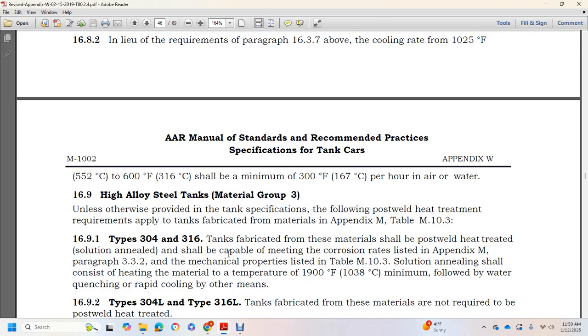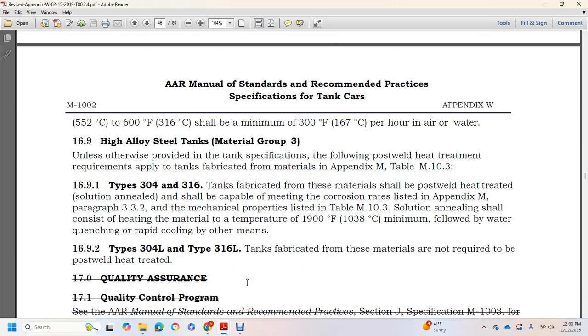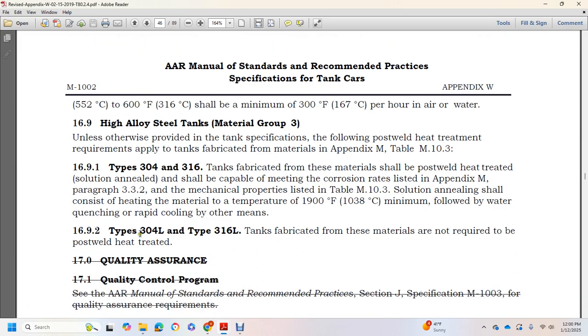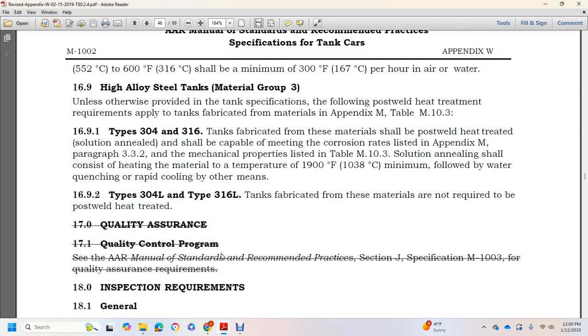Alloy steel tanks, material group 3. Unless otherwise provided by the tank specification, the following post-weld heat treatment requirements apply to tanks fabricated with materials listed in Table M10-3. Type 304 and 316 tanks fabricated with these materials, if post-weld heat treated by solution annealing, should be capable of meeting corrosion requirements in Appendix M, paragraph 3.3.2, and mechanical properties listed in Table M10-3. Solution annealing of the shell consists of heating the material to a temperature of 1900 degrees Fahrenheit minimum, followed by water quenching or other means of rapid cooling. Type 304L and Type 316L tanks fabricated with these materials are not required to be post-weld heat treated.